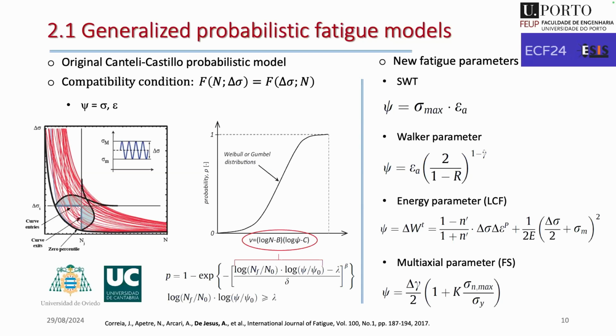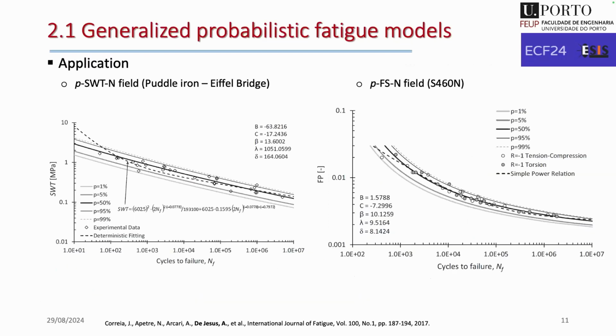And actually, this can be applied for different and more complex fatigue damage parameters, where, for example, mean stress could be included in the fatigue parameter, or we can play with energetic parameters, or even use this model for multi-axial fatigue, using multi-axial fatigue parameters like the one we are seeing here, known from Fatemi and Socie. So this was immediately explored in different fields, in different materials. For example, materials from old bridges in Portugal with the SWT parameter, or multi-axial fatigue with structural steels, were explored.